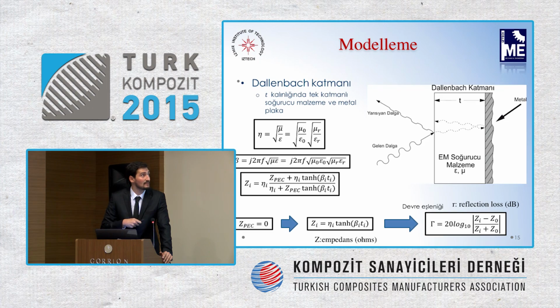In modeling, I won't go into details. There are similar structures, especially the Jaumann layer. It's the same. Transmission line theory is mimicked here. Between the surfaces, impedance values are important, and they have to be in harmony with the moving wave. And when these impedance values are extracted, it leads to reflection loss. Thanks to the equations, we can have a result. And there are some variables here, thickness or the type of the absorbing material. So based on material, it can be dielectric or it can be magnetic conductive.